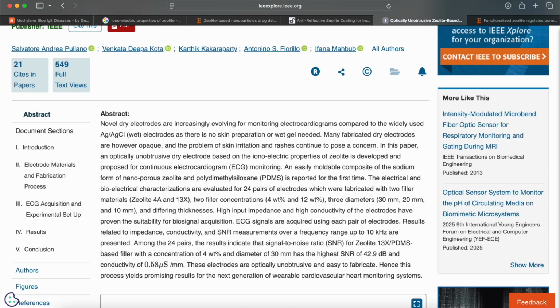An easy moldable composite of the sodium form of nanoporous zeolite and PDMS is reported for the first time. The electrical and bioelectrical characterizations are evaluated for 24 pairs of electrodes, which were fabricated with two filler materials, zeolite 4A and 13X, two filler concentrations, 4 weight percent and 12 weight percent, 3 diameters, 30 millimeters, 20 millimeters, and 10 millimeters, and differing thicknesses. High input impedance and high conductivity of the electrodes have proven the suitability for biosignal acquisition.